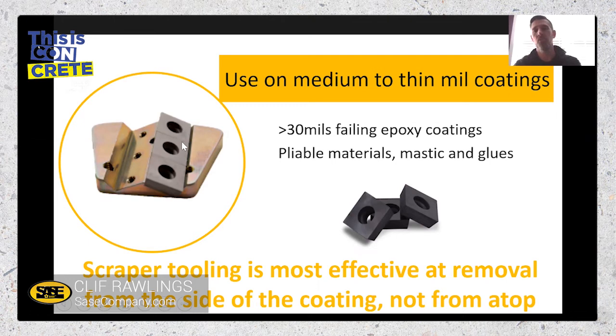These are awesome tools for really sticky, gummy glues. And what's nice about this is because of the smooth surface that you see here, it doesn't leave a rough profile at all. So you can follow this up easily with an 80 grit metal bond, sometimes even just a hybrid, like a 50 or 50 hybrid sometimes. Or if you're doing wet, you could go 100 hybrid behind it. So you're not even required sometimes to do a metal if you have a smooth surface below the glue. This is not leaving a profile. So that's kind of the beauty of this tool. If you don't need to cut aggressive and don't need to cut deep, and you're just trying to cut glue or mastic off, I'd go to this tool because you're not going to have to deal with some deep scratches like the PCD type tools will leave behind.